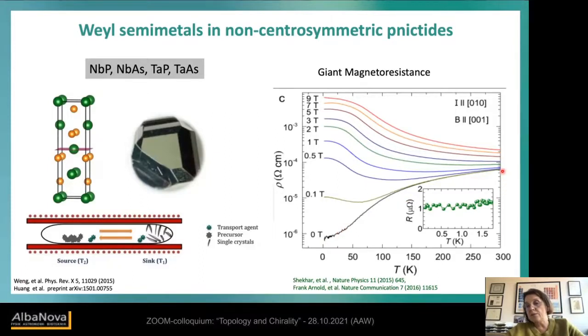And you see at zero magnetic field, the material looks more like a metal, but in the moment when we apply a magnetic field, and this is very typical for all the semimetals, Dirac and Weyl, we get a big change over orders of magnitude in the resistance. So the magnetoresistance is like millions. You might remember there was spintronics and there was magnetoresistance of 100% also. And this has drawn attention because you could make read heads out of this, but here this effect is much larger. And if you see the upper curves in the magnetic field, it behaves more like a semiconductor, but then we would expect it goes up and up and up. And it's also very typical for all these materials that we have the plateau here, which we think is assigned to the surface states, which are there in this material in the magnetic field.